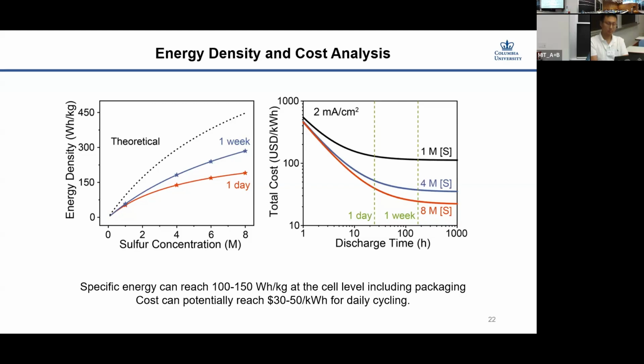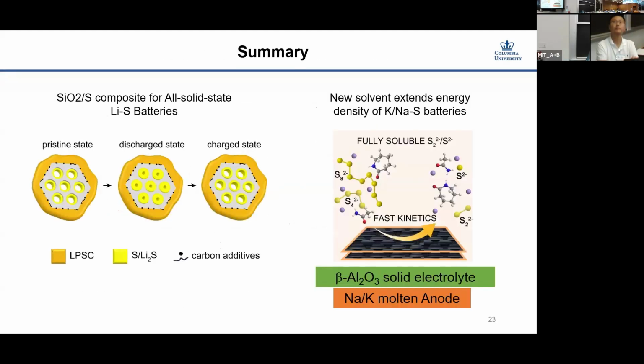We may also draw some preliminary cost analysis to see whether it is really attractive for large scale application or not. In short, energy density wise it can reach about 150 watt hour per kilogram, depending on how much is discharged. And the cost can be about 30 to 50 dollars per kilowatt hour at the cell level. So it should be attractive for large scale application.